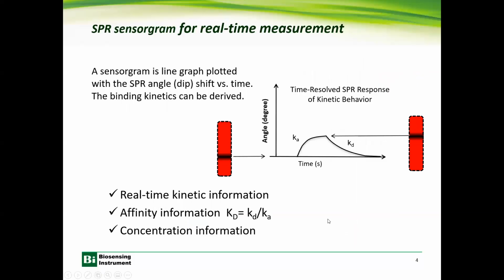And then you will obtain the spectrum, the so-called SPR sensorgram, which basically records the whole process of the association and the dissociation of the reaction. By analyzing this association and dissociation, you can get kinetic parameters such as k-on, the rate constant for the association, and k-off for the dissociation, and of course the affinity, which is equivalent to the equilibrium constant of the reaction. So this is how SPR works.